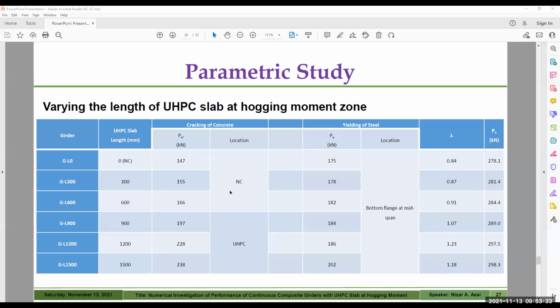increased significantly. For the yielding load, yielding of steel starts at the bottom flange at the midspan section, and the value of the yielding load increases significantly with the increase in the length of UHPC slab. If we define a parameter lambda, which is the ratio between cracking to yielding load, we'll see that the value of lambda is less than 1 for the length from 0 to 600 millimeter, and is higher than 1 for lengths from 900 millimeter to 1500 millimeter.